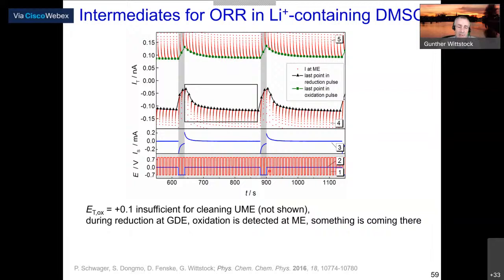If we make again a reduction pulse at the gas diffusion electrode, the current again breaks in. So that is all what we expect. This is not too surprising. However, we then also looked at the cleaning pulses, and there was something which was very strange. At the moment when less oxygen entered the cell because the gas diffusion electrode made the oxygen reduction by itself, we see that we get higher currents for the cleaning pulses. And it should not be the case. At least my naive initial understanding was that this should not be the case. So why do we have more to clean from our microelectrode if less oxygen enters the cell?